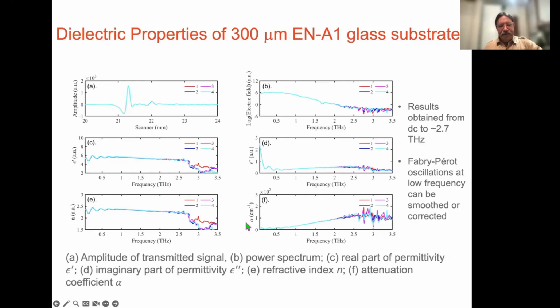Here is the refractive index. So here is ENA1 glass. So we get a good measurement out to about 2.7 terahertz. Out here, we reach the noise floor, so this is not useful information. Here's the absorption coefficient. Again, we're going to hit the noise floor out here. Notice the rapidly rising losses.